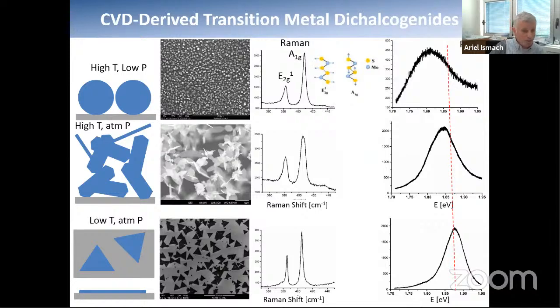But when you go down to a single layer, the PL emission increases dramatically, because it turns out that from the bulk to the one layer, there is a transition from an indirect to a direct band gap semiconductor. So here you can see an example of single crystal domains, in this case MoS2, and every domain like that is a three-atom thick material, the transition metal at the center and two chalcogen atoms, bottom and top.